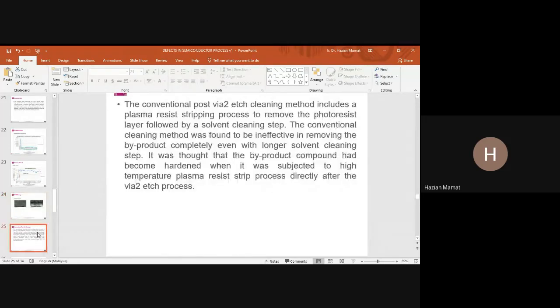The conventional post via2 etch cleaning method includes a plasma resist stripping process to remove the photoresist layer, followed by a solvent cleaning step. The conventional cleaning method was found to be ineffective in removing the byproduct completely, even with a longer solvent cleaning step. It was thought that the byproduct compound had become hardened when it was subjected to the high temperature plasma resist process directly after the via2 etch process.